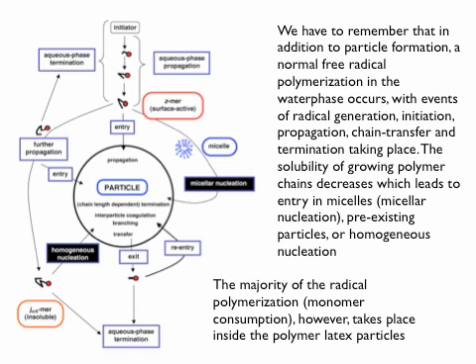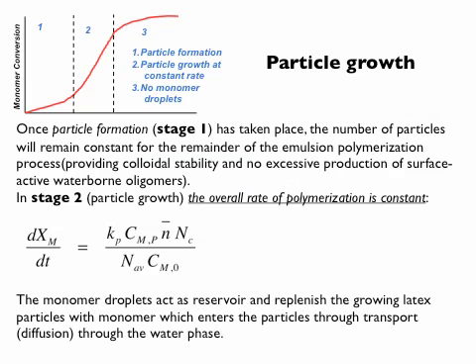All these things happen, but the majority of the polymerization reaction happens inside the particle. Remember, only a few units of styrene get added in the water phase — two, three, four, five, six, maybe — until I hit j-crit and am classed as a particle. So everything else happens in the particle. Once I have my particle and I've passed the particle formation stage, let's look at the particle growth stage. After stage one, with a stable set of particles and no further nucleation, I enter phase two.